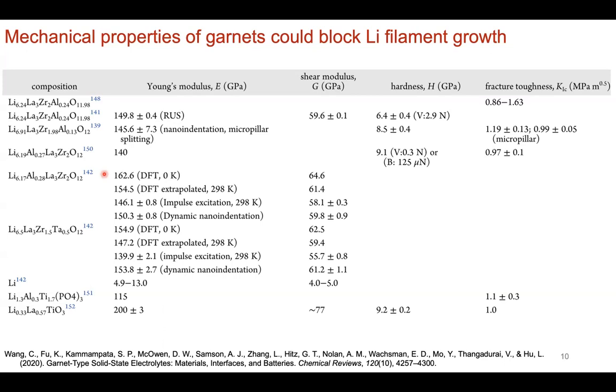So the theory has been that if your elastic modulus is high enough, then this material can block and impede lithium filament growth. Well, that as a first pass is true, but the situation is more complex, as in you could have softer polymeric materials that will also impede lithium filament growth based on the chemistry of the polymer. So it's not always true, but it is a good guiding principle to start off with. So this is advantageous for this particular material. So that's what we see here. We see extremely high elastic modulus here, for a variety of compositions with aluminum substitution in lithium lanthanum zirconate type compounds, or LLZO.